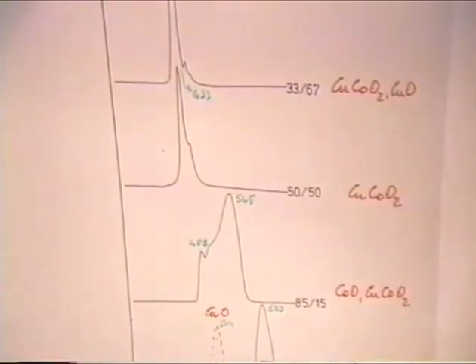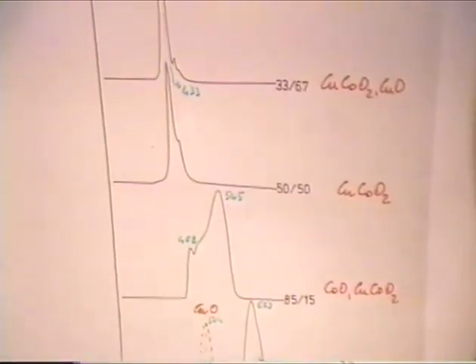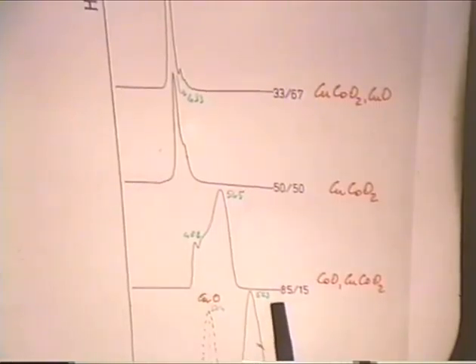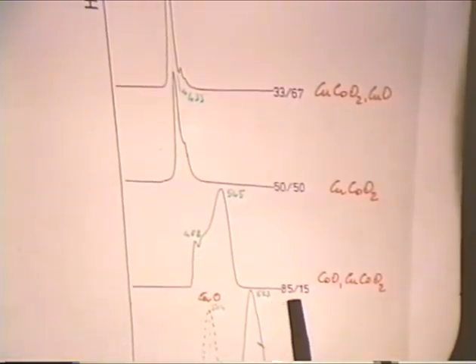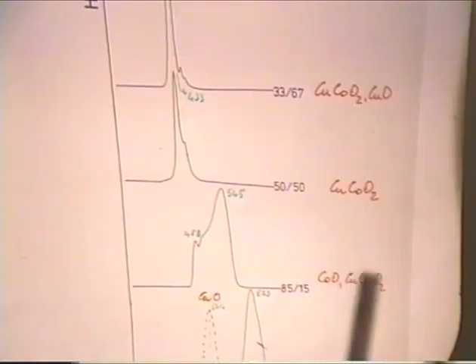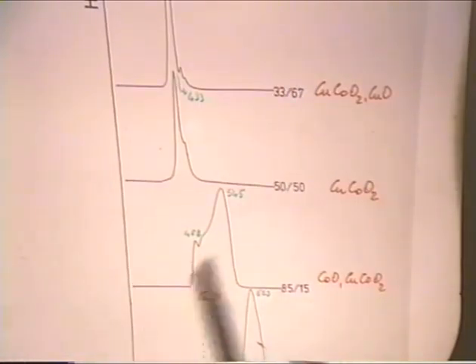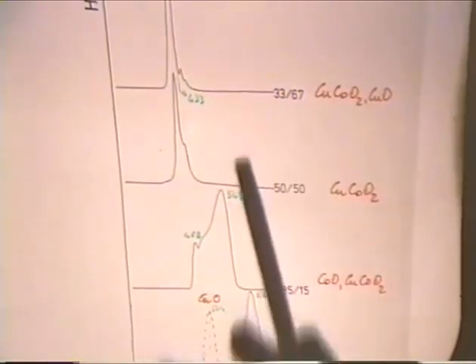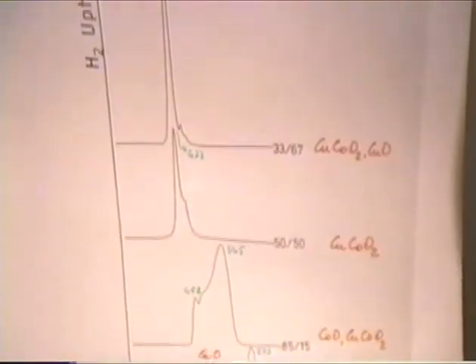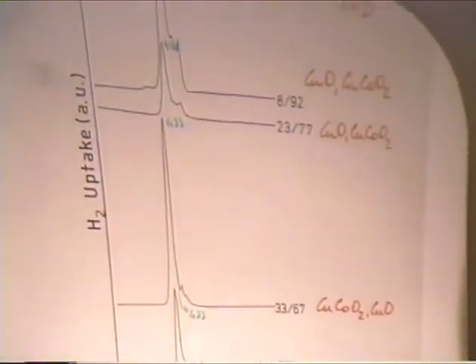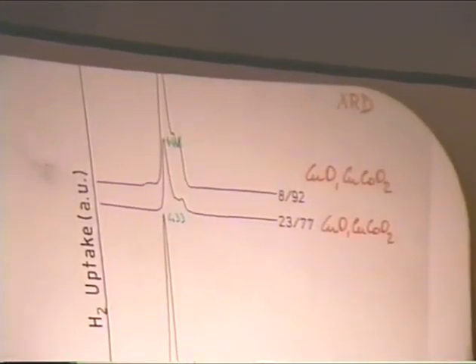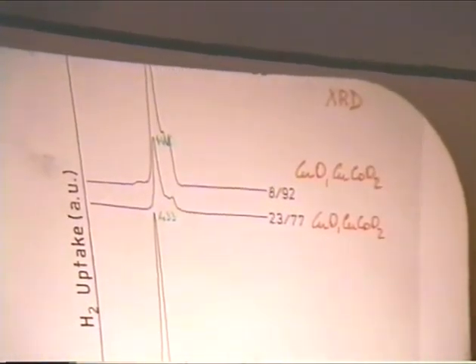But the first addition of copper produced a dramatic change in the reduction profile. Look at the catalyst having a cobalt-copper atomic ratio of 85-15. The reduction profile of this catalyst was characterized by at least two peaks, and both of these peaks are shifted remarkably towards lower temperature. As the copper content was further increased, a further shift towards lower temperature and a narrowing of the reduction profiles were observed.